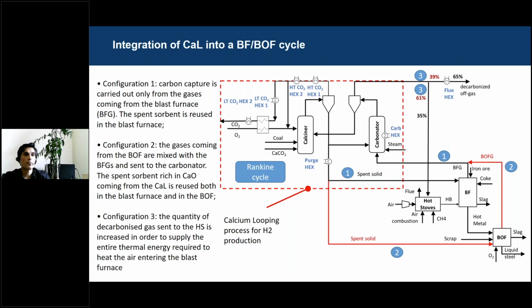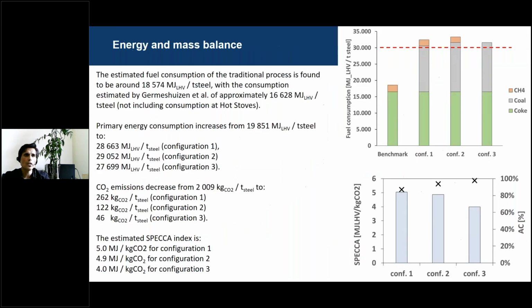Just an important thing is that thanks to the calcium looping, we can integrate also, and this is a very important aspect, a Rankine cycle which can recover the excess heat from the calciner, because as you already know, the calciner works at more than 900 degrees, so we can recover good quality energy. But we can also recover a part of energy from the carbonator, because in the carbonator there is heat released by the reaction of CO2 with the calcium oxide. Let's see how the energy and mass balance is.